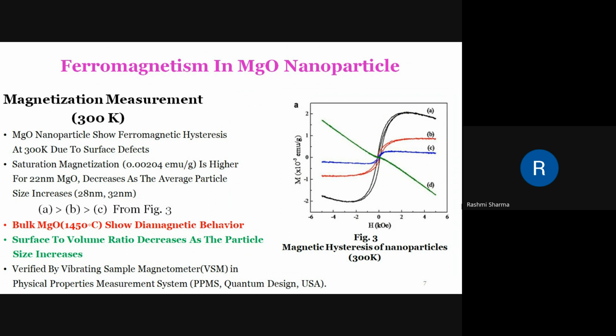So what is the reason for this? It is that ferromagnetism is caused due to the defects present at the surface of the particles. When the size increases, the defect concentration decreases because of the decrease in surface to volume ratio, so it results in a decrease in the ferromagnetic property. So it is clearly visible that when the size is increasing, the ferromagnetic property is decreasing, and the bulk material shows diamagnetic behavior because of the low vacancy concentration at its surface. As I explained, it is because the surface to volume ratio decreases as the particle size increases.